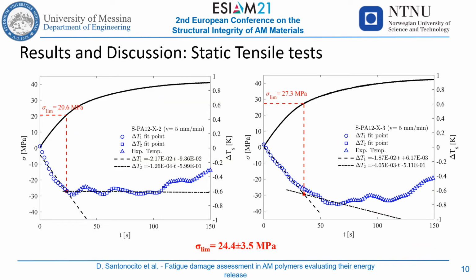While test 1 and test 3 show the same temperature trend with a gradual transition between phase 1 and phase 2, the second one has a more marked transition with a value of the limit stress considerably lower than the others. The average limit stress for the three considered tensile tests is equal to 24.4 ± 3.5 MPa.